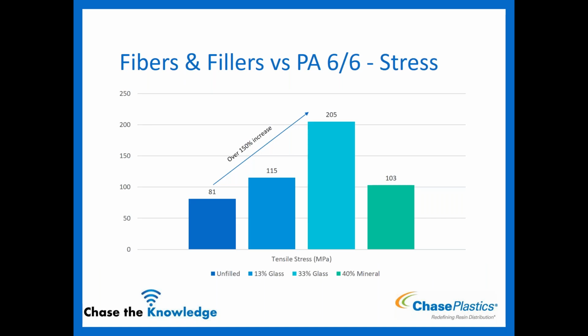So in this graph, you'll see the tensile strength or tensile stress, depending on the word you'd prefer to use for it. But you could see you go from an unfilled at 81 all the way up to a 205 at 33% glass. Again, add more glass, gets better, but you're looking at a 150% increase. So huge increase in your performance there if you're using a standard unfilled 6.6 and your application requires it to be a little bit stronger, a little bit more strength out of it.